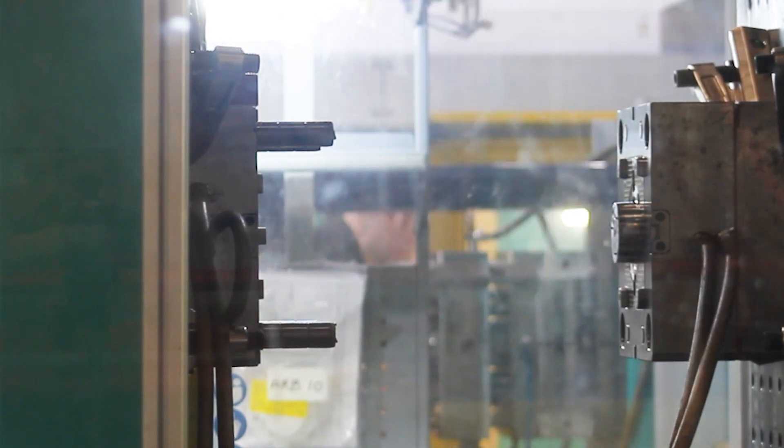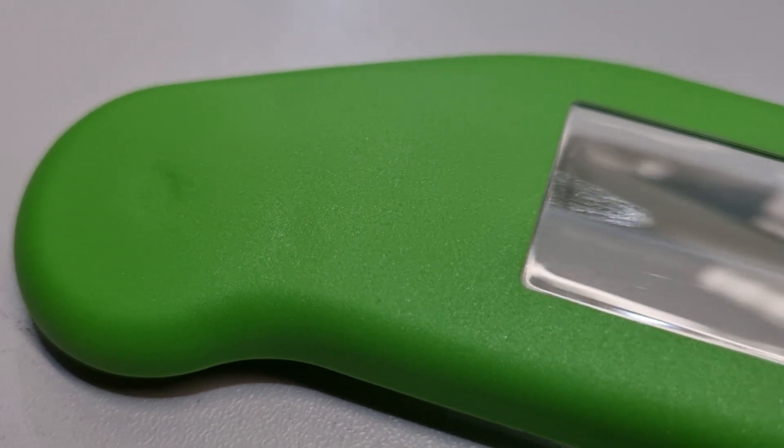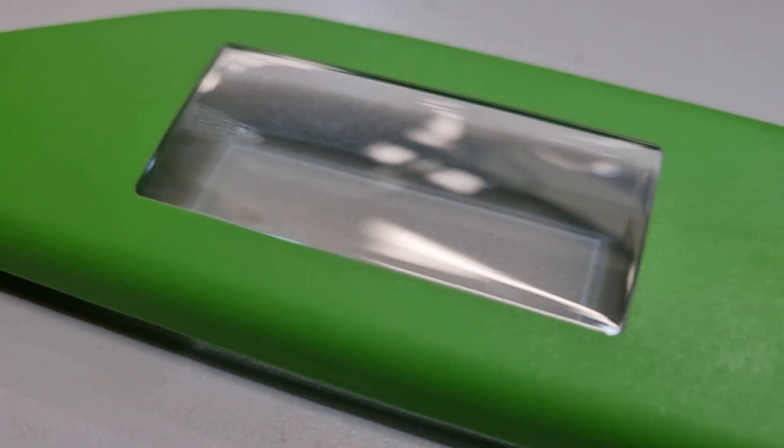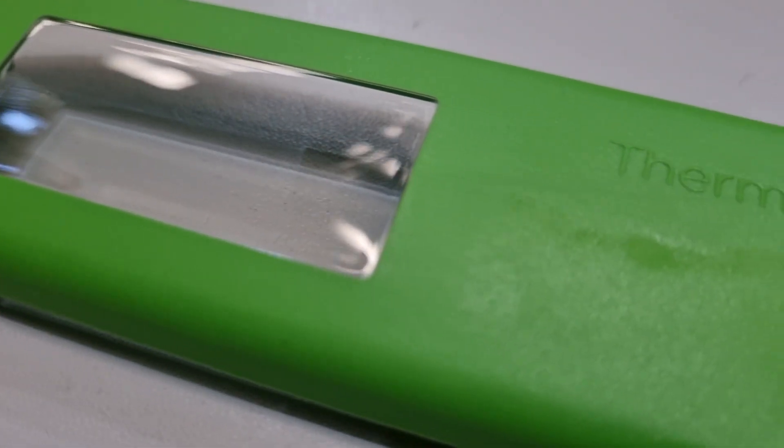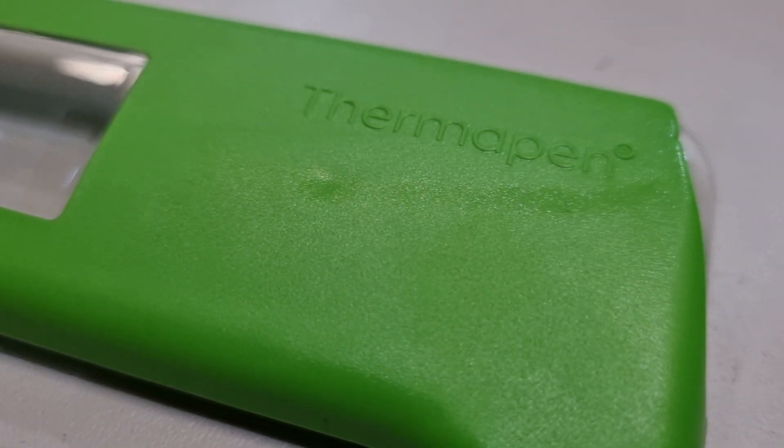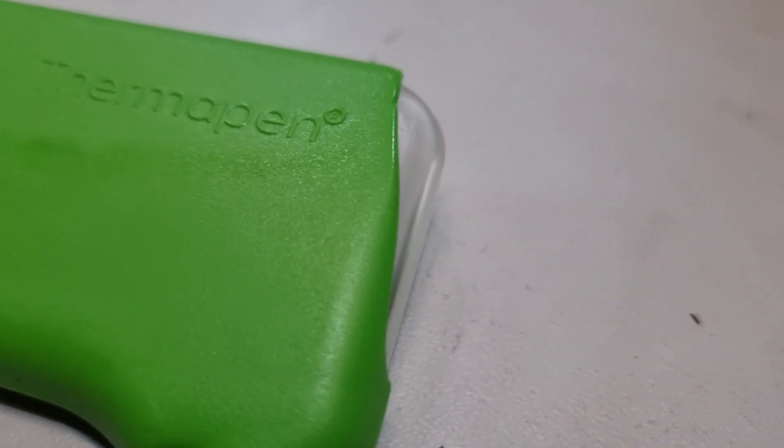Having the correct packing pressure before this stage is absolutely vital. If the material has not been condensed enough, the shrinkage will be uneven, which can lead to sink marks and warpage.